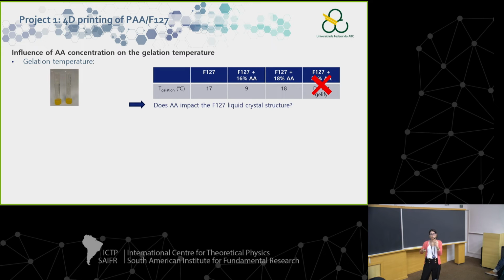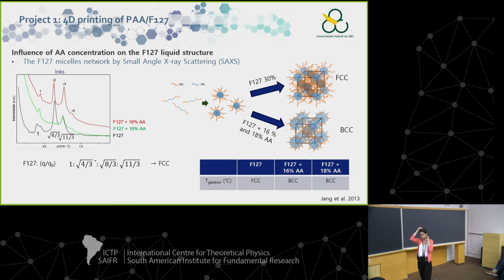And then, from a fundamental point of view, we wanted to know if acrylic acid can impact the liquid crystal formed by Pluronic micelles. So we went to Campinas, to the same place that you will visit tomorrow, and we performed SAXS measurements. It's nice because yesterday Anton Paar already explained how SAXS works, so I don't need to. Basically, we get the scattering vector as a function of intensity. We look at the peak position and at the ratio between this first peak and the other ones. Depending on this ratio, we can determine which liquid crystal structure is formed.